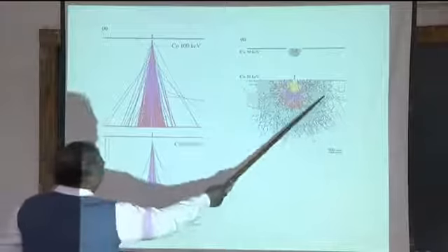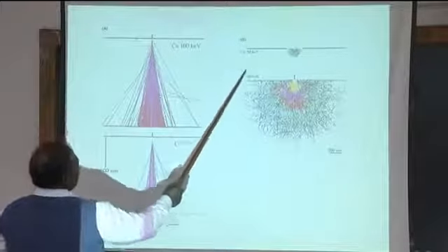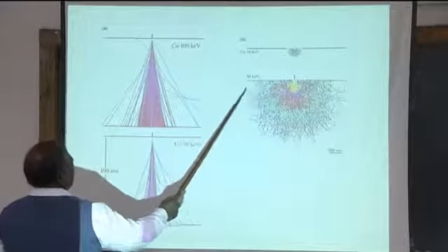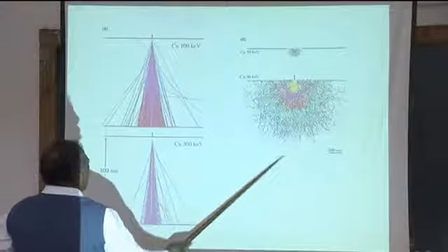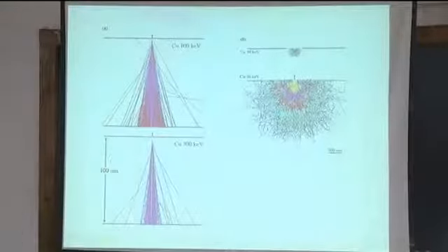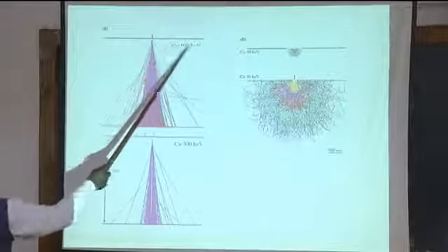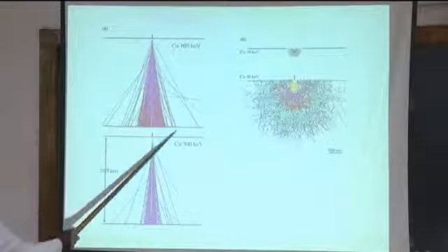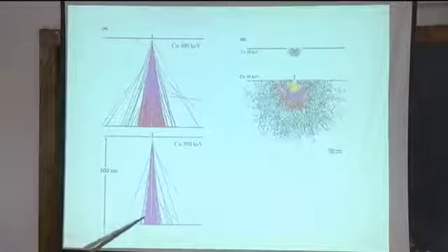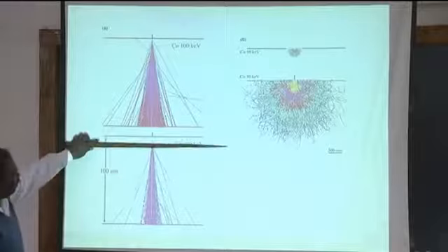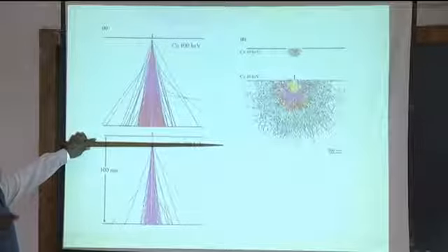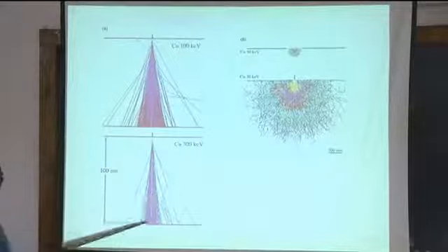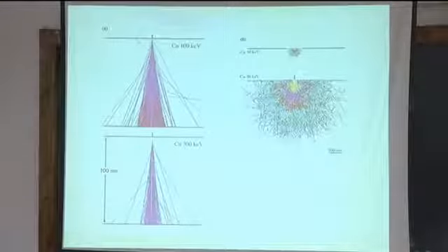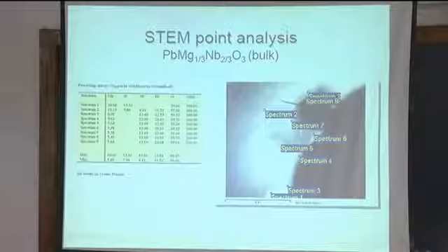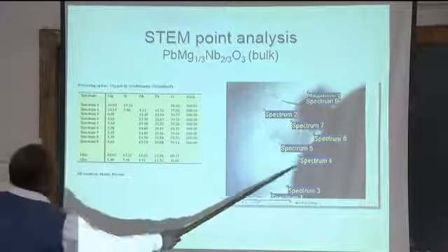SEM, you see the accelerating voltage. This is the sort of accelerating voltage used in SEM. So you see the interaction volume. It's very large. As against that, you see in a TEM, the material is the same. 100 kV, this is the broadening. 300 kV, this is the broadening. If your sample is kept thin, virtually there is no real broadening, and you can reduce your lateral resolution to very, very small numbers. And we can get spectra from a very localized region.